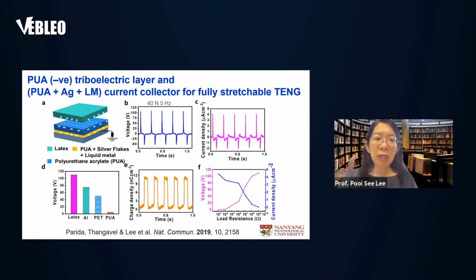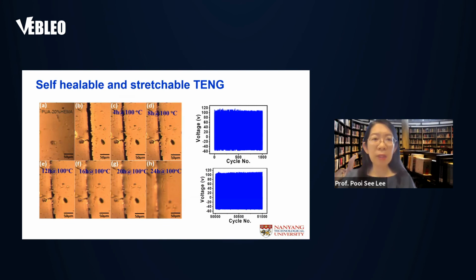harvester. In this case, the harvester is made of the polyurethane acrylate, as mentioned, with the counter contact of a latex or any other contact like aluminum PET as well. So it works well, and it also leads to not just stretchability, but self-healing ability. So the healability is shown here with a cut or so-called bifurcation. We can see obvious physical damage, but under a certain thermal budget, the self-healing of the material can be fully recovered, which includes the electrical and mechanical healability.